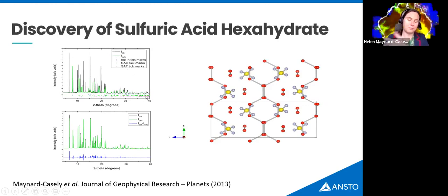I did a number of compositions. But you can see there's some missing peaks. So the green line is my model for the sulfuric acid octahydrate, and those black ones that aren't being modeled suggest that there's something else there, that there's a different phase. And playing around with the compositions, and you can see that one of the nice things about the synchrotron is we get very high resolution data, so we can go forward and solve the structure, I discovered that there's actually another form, sulfuric acid hexahydrate, so slightly less water in the crystal structure.